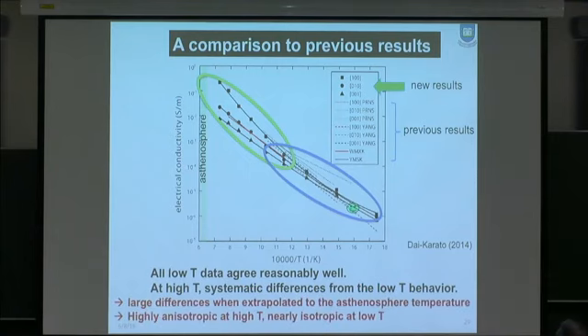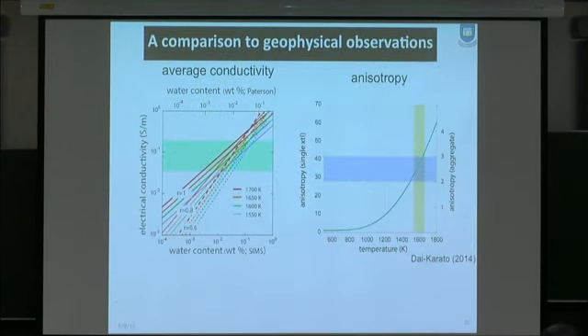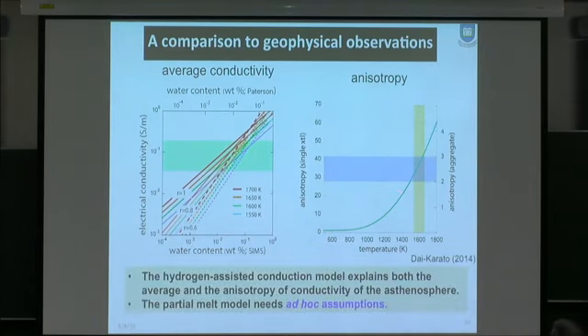And then if you use those high temperature results, you can explain both the magnitude of conductivity by plausible temperatures and water contents in the asthenosphere, which is consistent with geochemical inference, as well as the anisotropy. So I would argue that the hydrogen-assisted conduction model explains both the average high conductivity and the highly anisotropic conductivity of the asthenosphere. If you were to explain those by partial melt, you really need to have a certain melt amount and a certain way of alignment of melt.